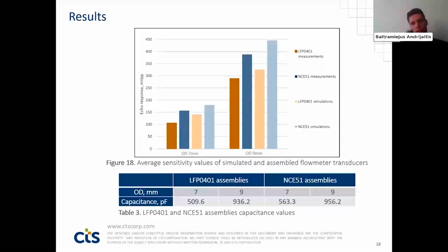Moving to the results, changing OD, outer diameter, from 7 millimeters to 9 seems to have had a significant effect. The performance increased by 2.7 times, which means with a small change of diameter, we can enhance performance significantly. This shows that lead-free ceramics could replace lead-based ceramics with a slight change in design.